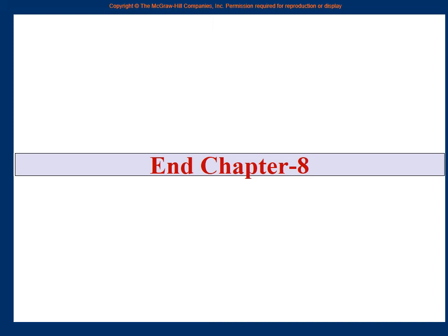After this initial background, and then we told you about cooling curves, that you see how do things cool. So for any metal, it is at very high temperature completely liquid. You drop the temperature until it starts to become solid. If it is a pure metal, because of latent heat of fusion, the temperature will remain constant until the whole metal has solidified. Once the whole liquid has changed into solid, the temperature will again start to drop.